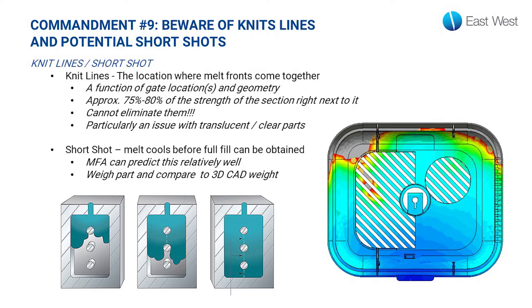Commandment nine is to beware of two molding anomalies: knit lines and short shots. Knit lines are areas where the melt fronts have recombined — as material flows around a feature and rejoins itself, that area is called a knit line, which is only about three-quarters as strong as the section next to it. Knit lines are unavoidable, being a function of part geometry and gate location, but we can ensure the knit line is not located in a high-stress area by adjusting the gate. A short shot is an area where the mold simply can't fill — material is pushed as far as it can go, and a chunk of the part is actually missing. Short shots can also be predicted with mold flow analysis.